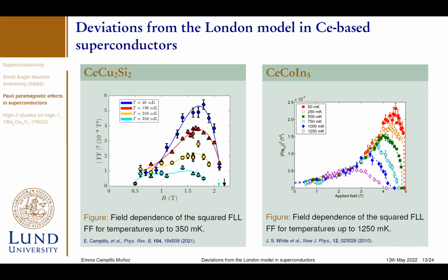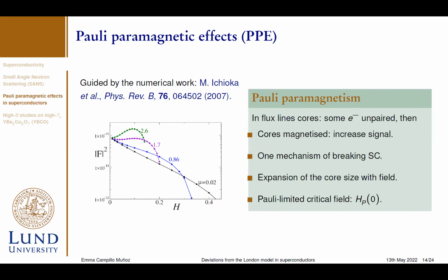So we have data that provide direct evidence of paramagnetic effects in CeCu2Si2. But we want a model that can describe this kind of behavior, either in temperature or in field. Following some numerical work previously developed by Ichioka, numerical calculations were performed to simulate the form factor of CeCoIn5 using different strengths of the paramagnetic effects. We found that the stronger the paramagnetic effects are, the bigger the peak that shows up close to Hc2.